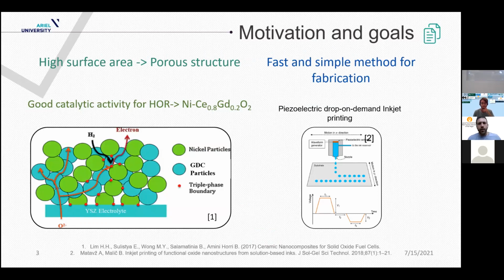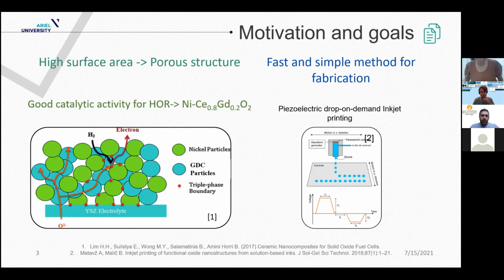In my work, the main motivation was to introduce a simpler and scalable technique to manufacture the anodes for the fuel cell. So my objective was to create high surface area anodes, so they need to be porous in microstructure. Also, they need to have good catalytic activity for the hydrogen oxidation reaction. So I chose nickel and gadolinium doped ceria as the materials of fabrication. Nickel is used as the electron conductive phase, and the gadolinium doped ceria is the ionic conductive phase. Both are critical for creating the triple phase boundaries, which are the active sites for the anodic reaction. And for the method of fabrication, I chose to use a commercial inkjet printer because it's fast and simple to operate.